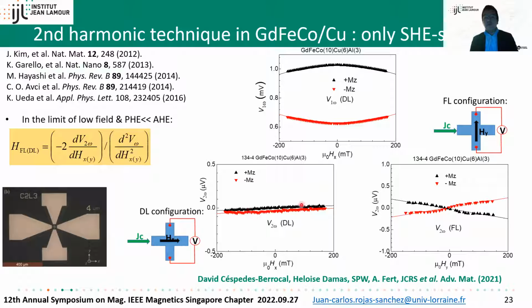And here, of course, we can see that the slope is quite weak, it's very small. That's because this sample is only gadolinium iron cobalt and copper. We don't have a good spin sink. Copper is a good spin decoupling material and not a good spin sink. So in order to improve the absorption of the spin current emitted from gadolinium iron cobalt, we can add another material that is a good spin sink, for example platinum and tantalum.